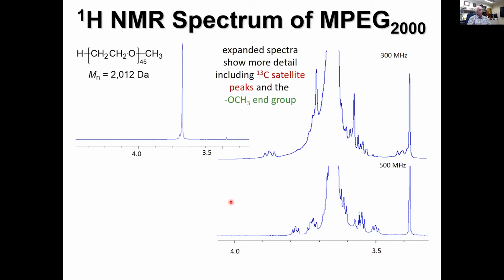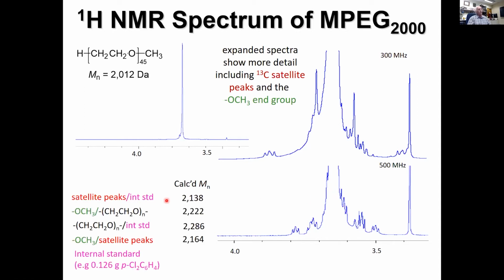We can do this in this particular case. We've done this with internal standards or by integrating the small methyl peak to the main peak of the polymer, and we typically get numbers that are roughly the same. Basically, the polymer is supposed to be 2000 Daltons. We find it's more like about 2150 or 2200 Daltons.